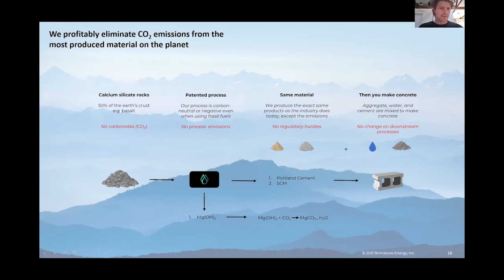The other clever thing that it does is it takes the silicate fraction and turns that into a supplementary cementitious material. In our case, our favorite supplementary cementitious material is class F fly ash. That's a conventional material that's made today. We can make an SCM that passes the ASTM standard for class F fly ash, but we can also make others.